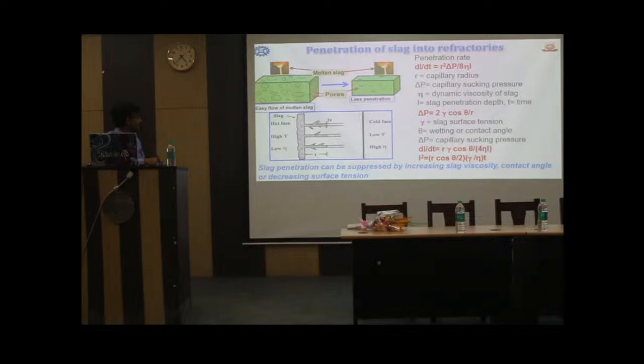Suppose this is a refractory, this is the slag zone and this is the hot face, and then slag can penetrate up to a certain length, this is L. Depending on the temperature at the cold face, if the viscosity is high, then ultimately it ceases to flow at a certain distance. So this L is the slag penetration depth, and eta is the dynamic viscosity. And delta P again depends on 2 gamma cos theta by R, where gamma is the slag surface tension and theta is the wetting angle. So ultimately, L depends on the pore radius, the contact angle, the surface tension and the viscosity.